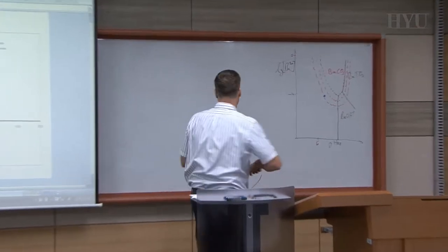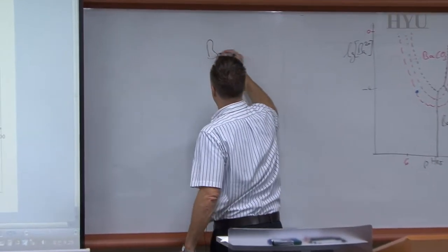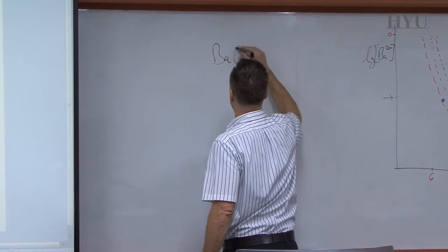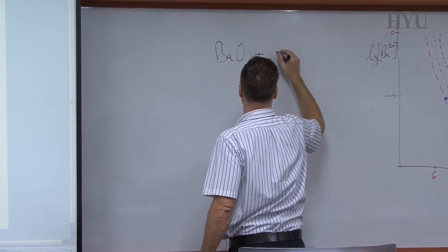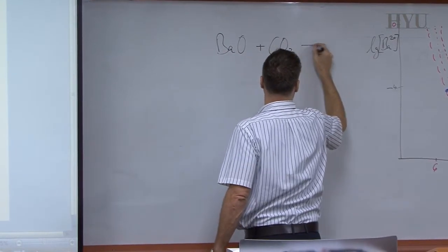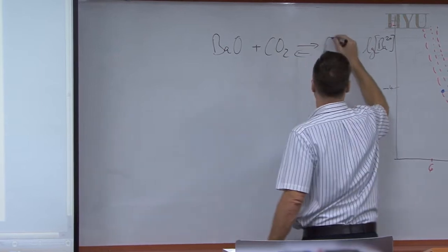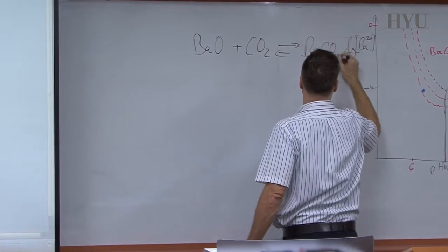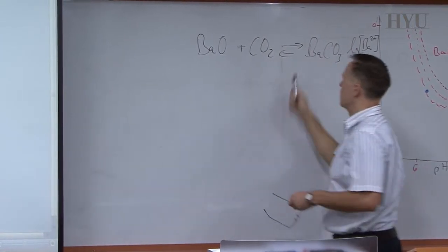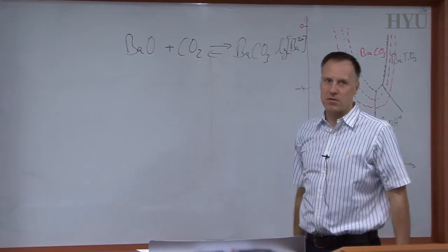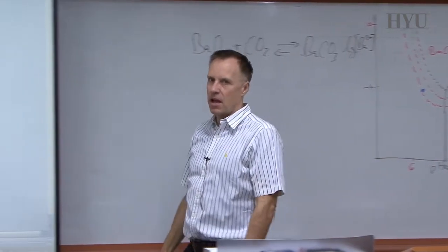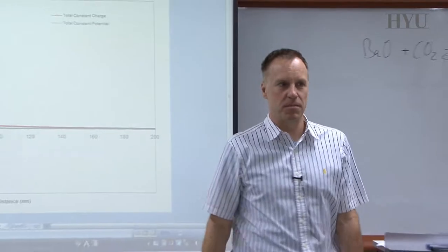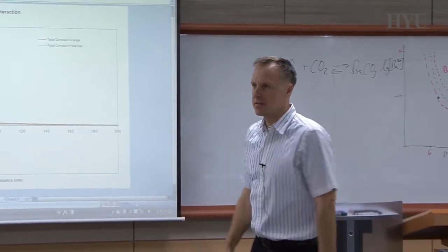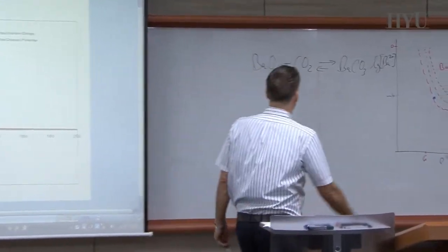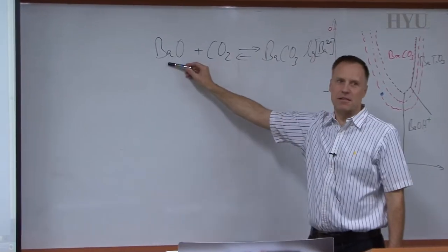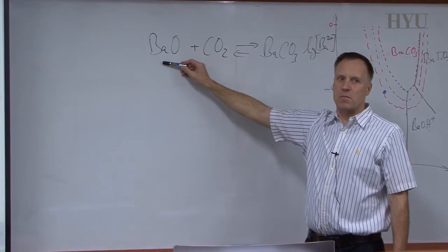So I help you a little bit. So you have barium oxide plus carbon dioxide. It's in equilibrium with barium carbonate. And of course, this reaction can happen in both directions. And if you want to heat treat the material, what happens? You're moving into this direction.